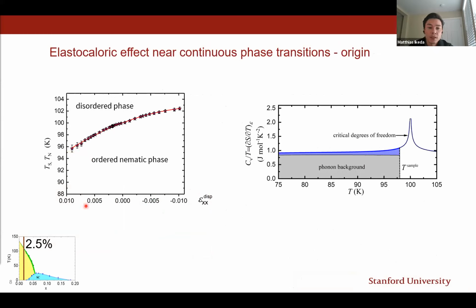And so in the figure on the left-hand side, I plot the nematic phase transition temperature for 2.5% cobalt-doped barium iron arsenide as a function of strain. And as you can see, the nematic phase transition is strain dependent here. Coming from the disordered phase and going through the phase transition into the ordered phase, of course, we expect an entropy change to occur. And this entropy change must also leave an imprint in the heat capacity over temperature, or in the heat capacity, and that quantity is shown in the figure on the right-hand side.